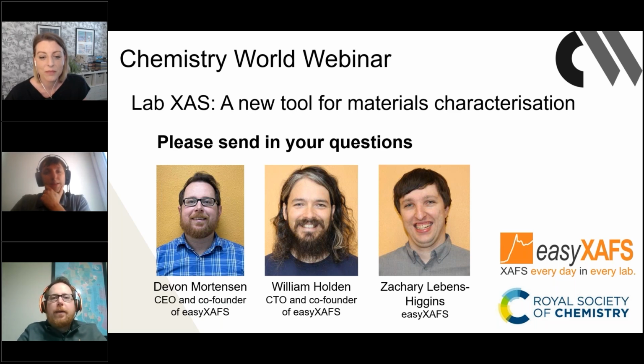Yeah, absolutely. So like I said, powders are pretty common. The method you would use for powder is, first, you want to determine how much of the material you need, and we have tools built into the software that will help you do that. Usually it's on the scale of a few milligrams. You want to make sure that you have a uniform sample, so you don't want isolated particles. So you want to grind it up. We'll usually add a binder material just to help it hold together. And that gets put into a die cast and pressed into a pellet. So that's for powders.